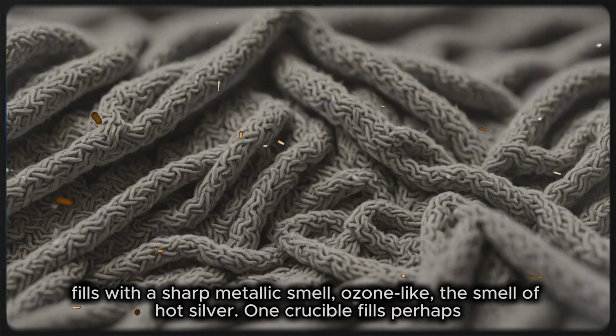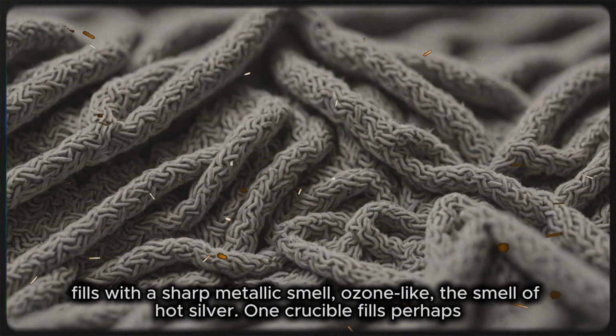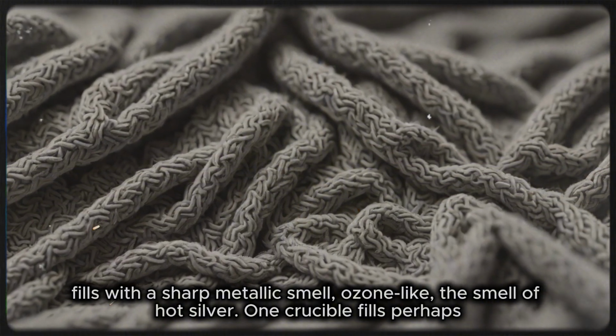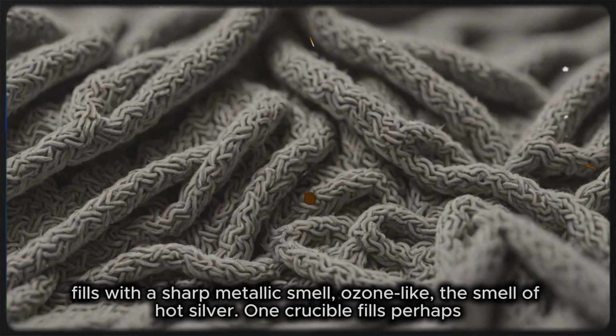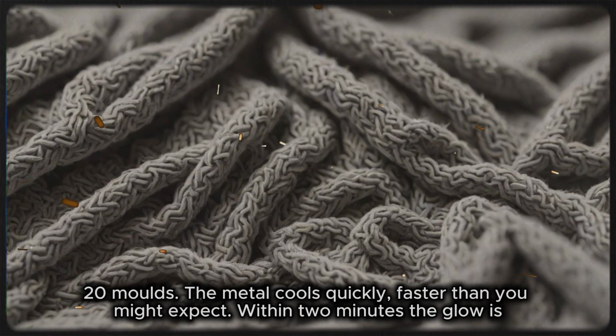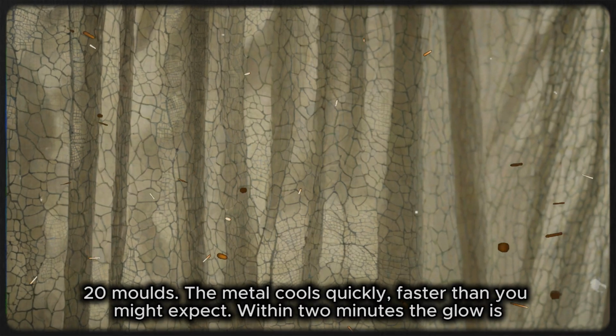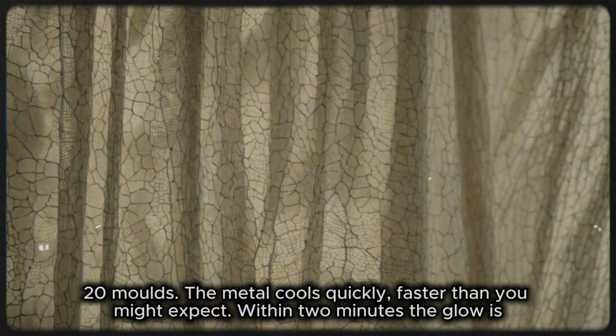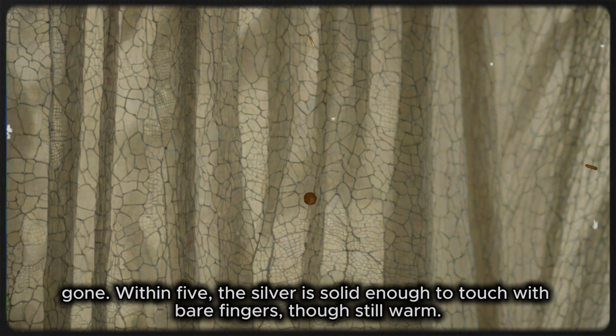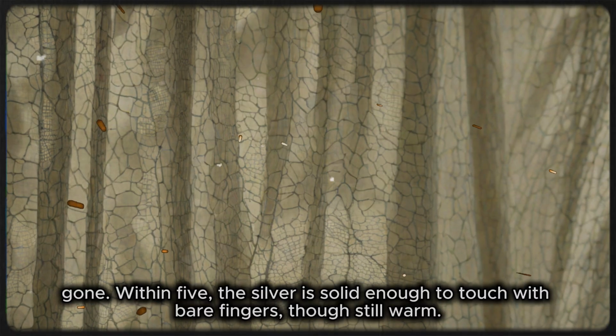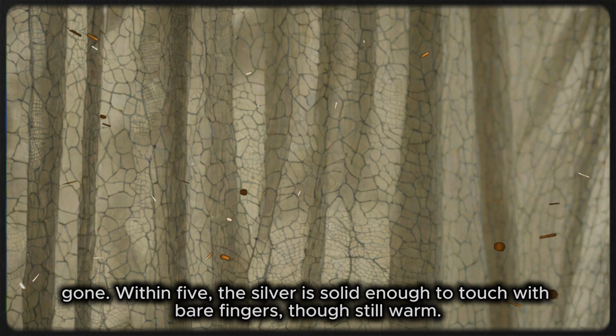The air fills with a sharp metallic smell, ozone-like, the smell of hot silver. One crucible fills perhaps 20 molds. The metal cools quickly, faster than you might expect. Within 2 minutes, the glow is gone. Within 5, the silver is solid enough to touch with bare fingers, though still warm. Within 10, the castings can be removed from the molds.